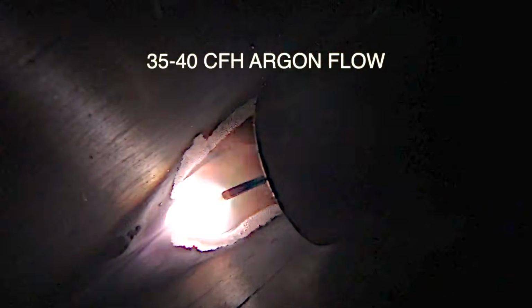So you need enough argon flow, but the sweet spot is fairly narrow. If you get too much argon flow, it acts a fool. The arc gets really erratic. You get spatter. It acts like you're trying to heat something up while you're trying to blow on it at the same time. So you've got to get the argon flow balanced where you have cleaning action, but still a smooth arc. And so for this, it's somewhere between 35 and 40. I don't have it quite dialed in perfect yet, but you could see that cleaning action right next to the bead. I'm still getting a little soot.